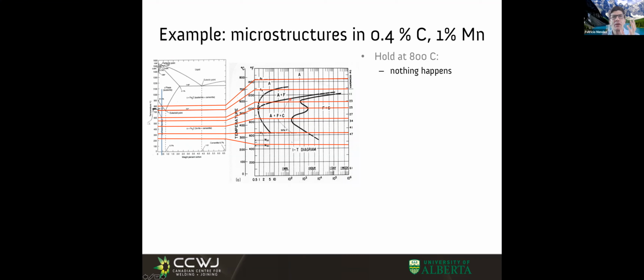An approximate way of knowing if you're gonna have pearlite or bainite is, you see the nose? Transformations above the nose tend to be pearlitic. Transformations below the nose tend to be bainitic. And look at this, very funny - in this steel in particular, the end of transformation has two noses. One nose for the end of pearlitic transformation, and another nose here for the end of bainitic transformation. And of course, if we quench down very fast, we would be crossing the martensite start temperature, and we would have all martensite.